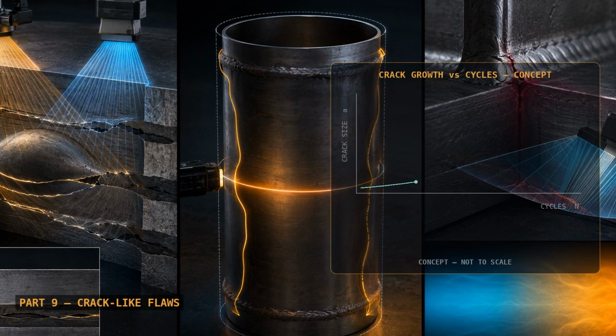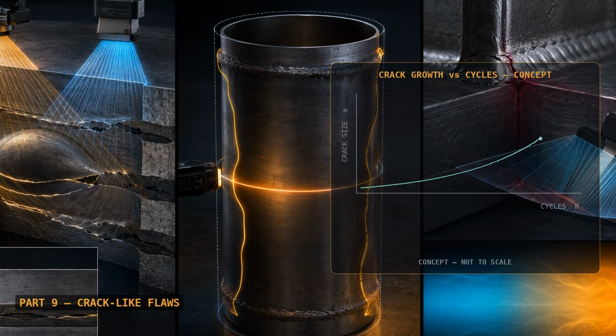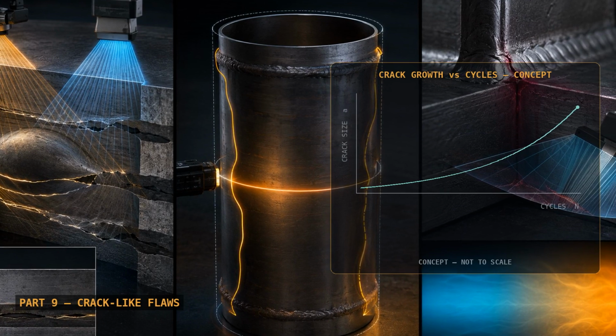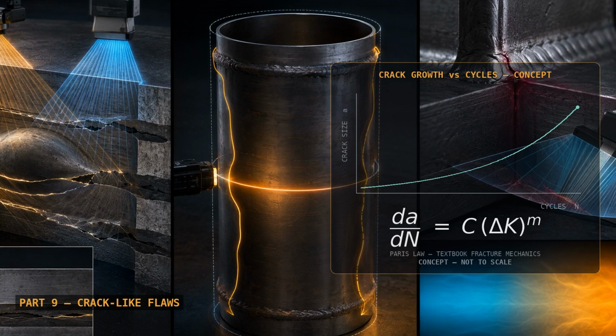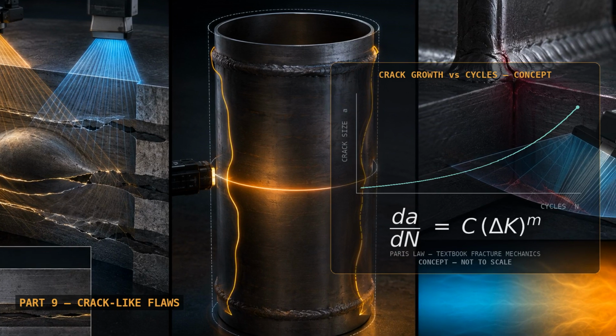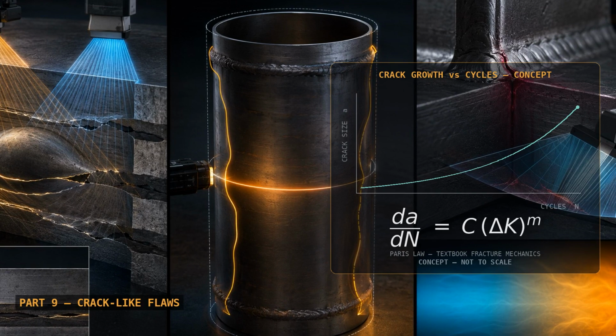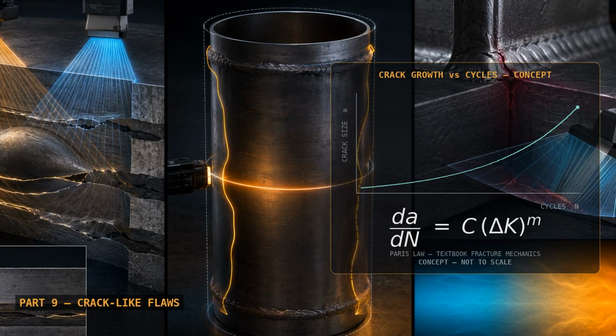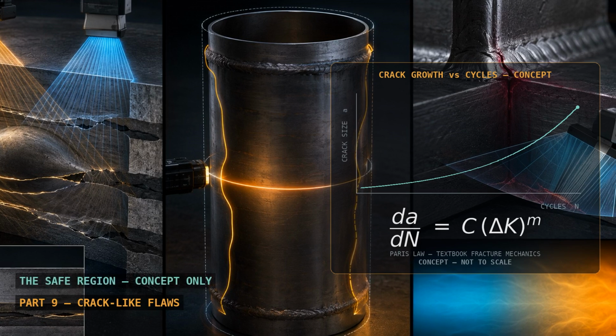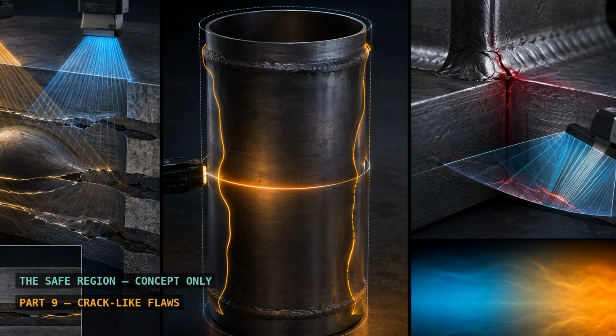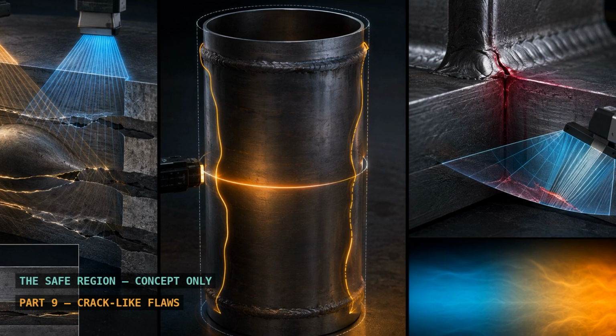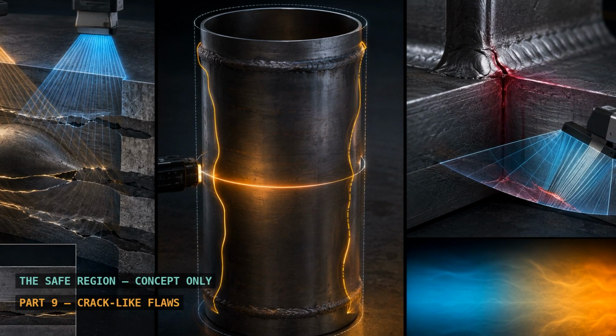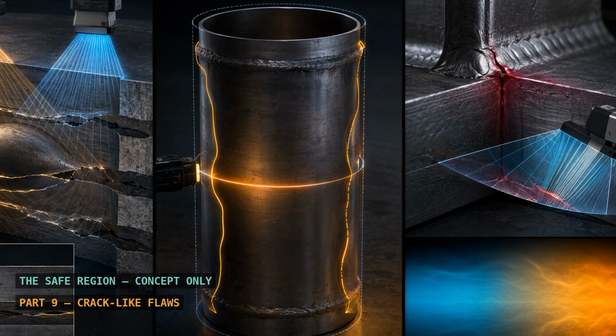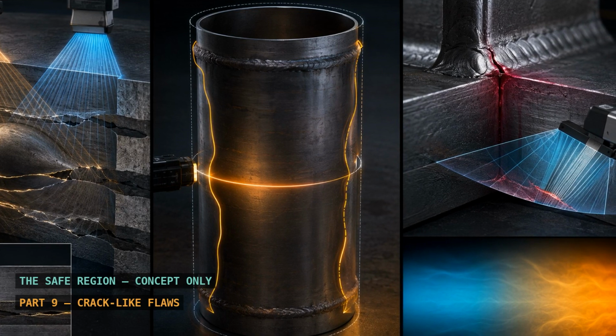Part 9. Crack-like flaws, the most safety-critical part of the standard. Fatigue cracks, stress corrosion cracks, grown weld defects. Found by magnetic particle and penetrant testing, phased array, TOFD, radiography. Accurate sizing is the hard part. The question: given flaw size, stress, and toughness, will this crack stay stable until the next inspection? Engineers picture the answer as a map with a safe region.